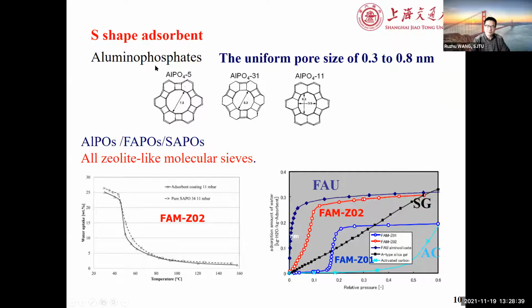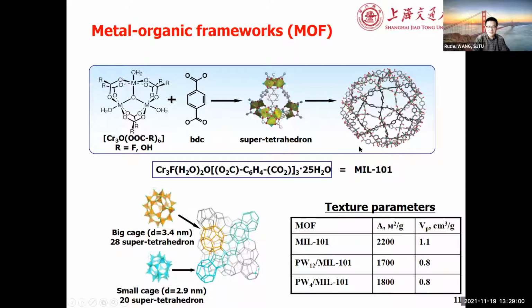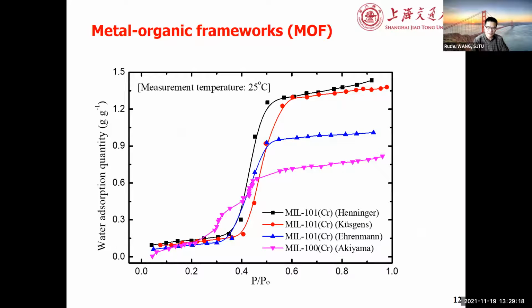And also there are some adsorbents very similar to MOF materials. Usually the adsorption jump is only about 0.3 or 0.2, but for MOF you could have an adsorption jump of maybe about 1. That's very huge. So this is for the MOF material. There are a lot of researchers in recent years, and it's a very hot topic for material scientists. Now it's also transferred to applications that try to use this kind of sorption adsorbent, especially this MOF material.